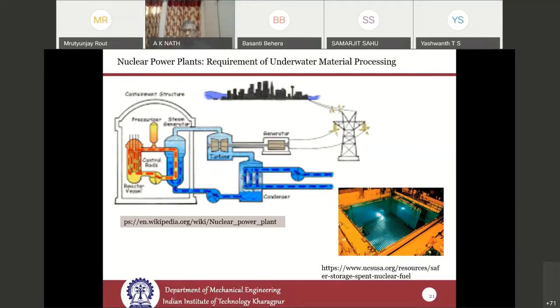...is put under water in a tank around 30 to 40 feet beneath water, so that the radioactivity gets absorbed in the water. Now you need to dismantle these materials to take out the burnt fuel and process it for storage of the waste material. Now, how to do this cutting of these materials, and that too underwater?